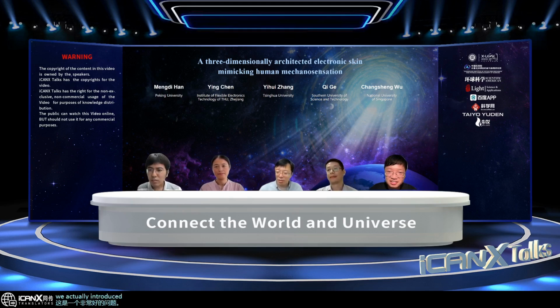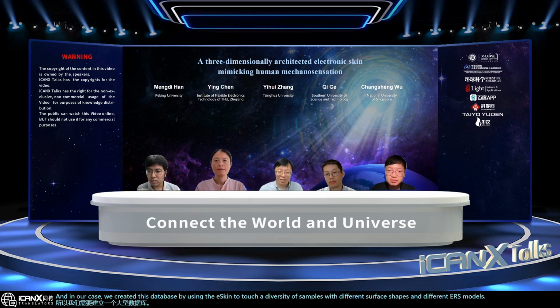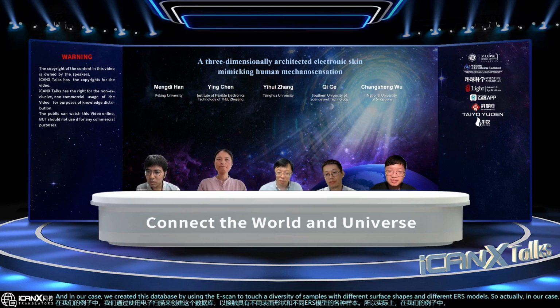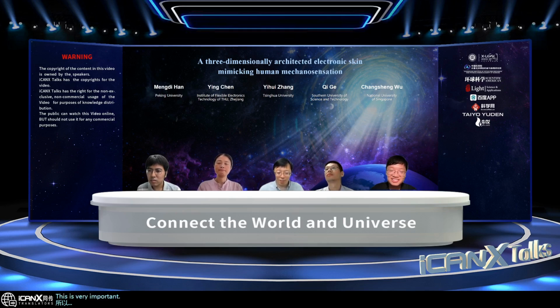This is a very good question. We actually introduced a machine learning algorithm for the prediction of elastic modulus. For the machine learning algorithm, it's very important to have a large database, so we need to construct a large database beforehand. In our case, we created this database by using the e-skin to touch a diversity of samples with different surface shapes and different elastic modulus. We have a large database consisting of around 30,000 samples. So this is a very important basis for the accurate prediction of different samples. Okay, thanks. Yeah, the data-driven approach is very interesting.